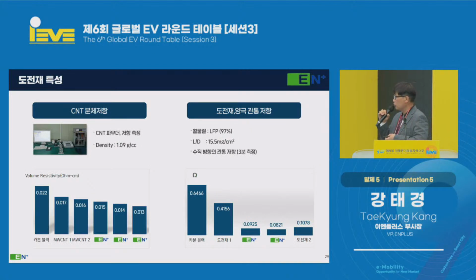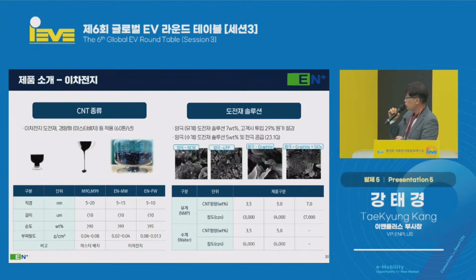Now, if you look at here, CNT, instead of saying yes or no, or it's good or bad, carbon black is about 0.022, and this is a volume resistivity, and the MWCNT is about 0.017. And if you evaluate the full cell, please use the conductive additive produced by my company. On the right side, you can see the cathode and also the conductive additive, how it is resisting. And in our case, you can see that it's not horizontal, but vertical. Vertical one is more important. And the carbon black, compared to that, about 10 times or 7 times, it's much better if you look at the resistance. Now, CNT types, I'll skip that.